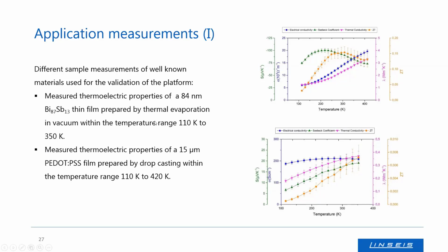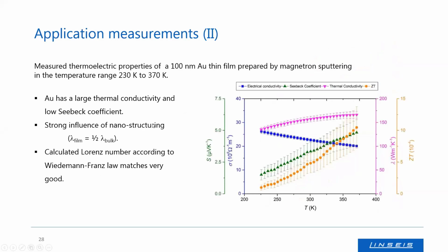The last example shows the measurement of a metal, of gold. The film was prepared by magnetron sputtering and had a thickness of 100 nanometers. Gold is a poor thermoelectric material. It has a large thermal conductivity and a low Seebeck coefficient. Again, the results are shown in pink, thermal conductivity, in blue, electric conductivity, in green, the Seebeck coefficient, and in yellow, the figure of merit.